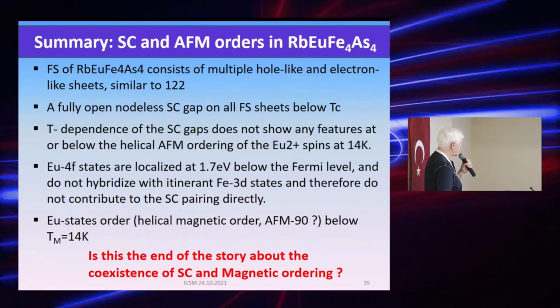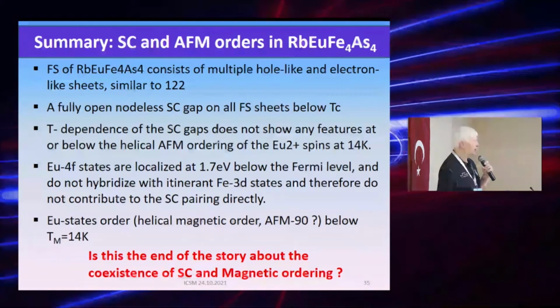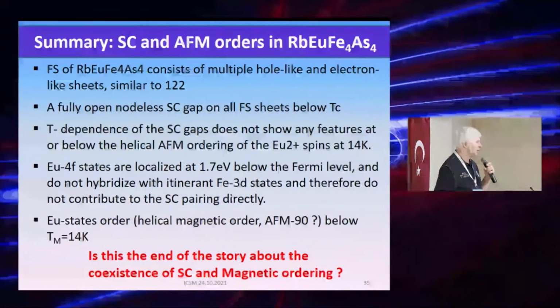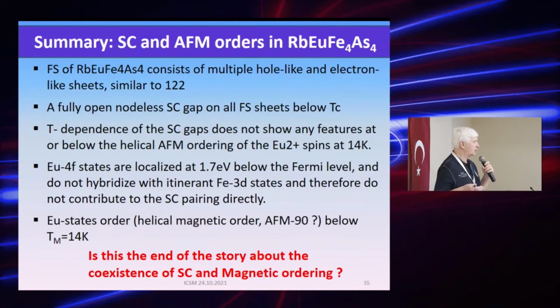Other experiments and calculations suggest that the europium states order in a helical structure, possibly with a structure where the direction of magnetization rotates by 90 degrees from one plane to another plane. And there are two factors: the electron layer, the superconducting layer, and the layer of europium are 1.3 nanometers away, too far from each other. And the second fact is that in energy they are located 1.7 electron volts away from each other.